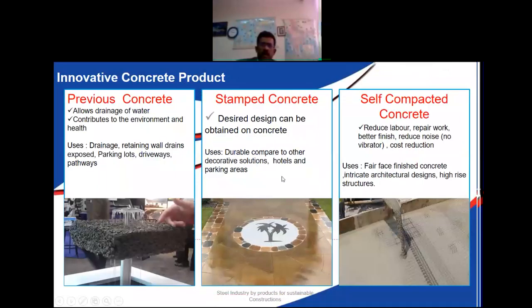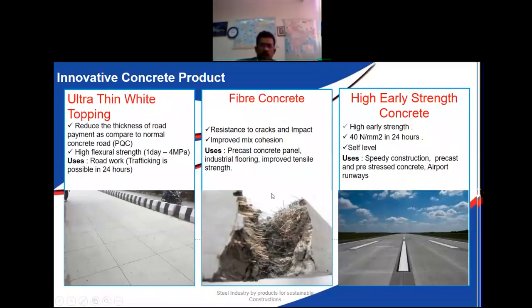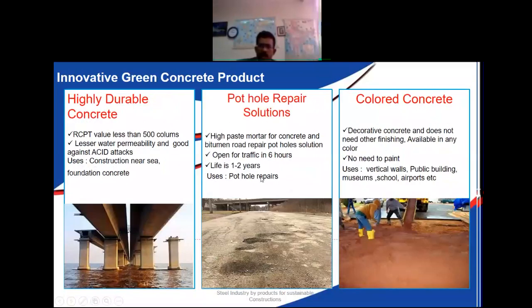And we can make special concretes using this slag industry byproduct: pervious concrete, stamped concrete, self-compacting concrete, white topping, fiber reinforced concrete, high early strength concrete using advanced modification in the admixtures, coastal environment high durable concrete, colored concrete. It's very good for colored concrete because GGBS is white in nature, so it reduces the demand for pigment. With a lesser pigment concentration, we can make colored concrete using this. Maintaining and repairing potholes, making high early strength concrete, we can do repair mortars.